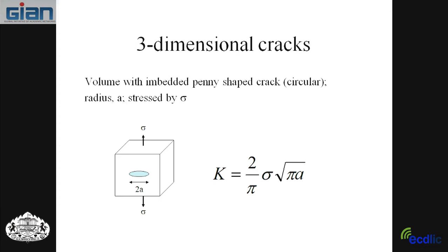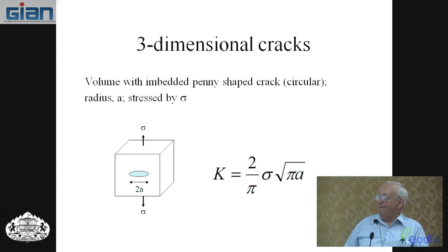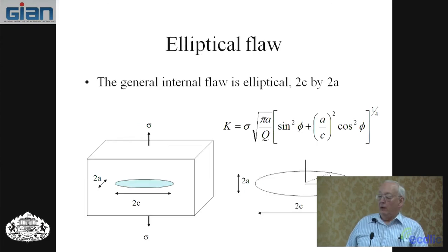Here's one, a little hard to imagine. It's called a penny-shaped crack. It's just a round circle crack embedded in this material, and here's the K solution for that. It always has that form, stress and square root of crack length, but sometimes it has different things out front. Now here is the most common 3D crack called the elliptical flaw. The elliptical flaw has a major axis of 2c and a minor axis of 2a. So this ellipse is embedded in that specimen.